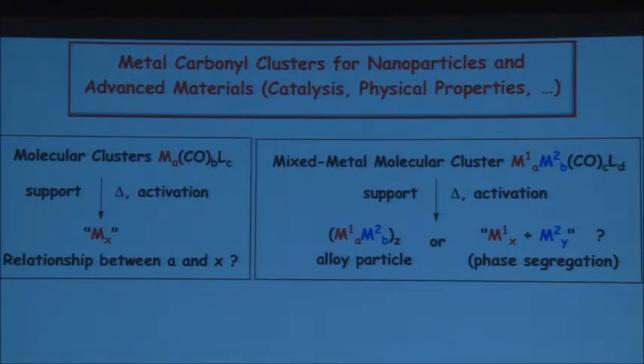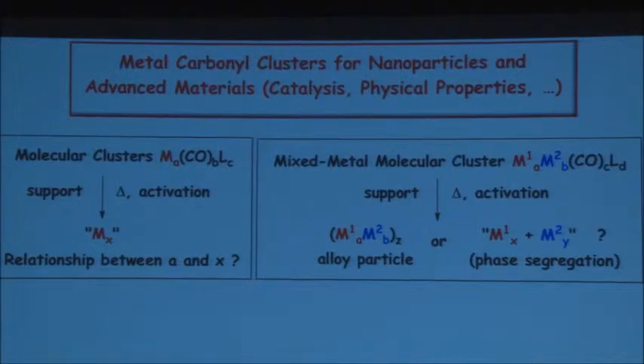We had an idea a long time ago, in the early 80s, to consider these metal clusters. The general formulation was Ma. Most of them came from metal carbonyl chemistry, to deposit them on inorganic supports, alumina, silica, something you may use for chromatography, for example. If you impregnate a solution of that, thermally activate, you should be left with a metal nucleus which corresponds to the core of your molecule. You've stripped off the ligands, you are left with a metal core.